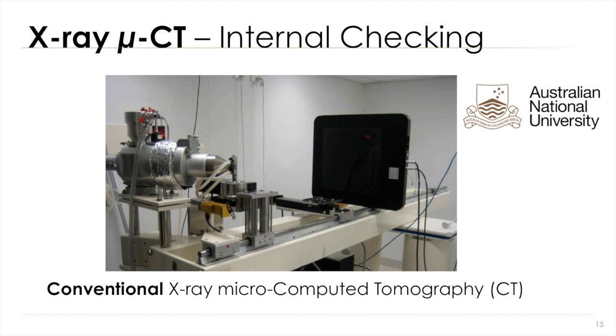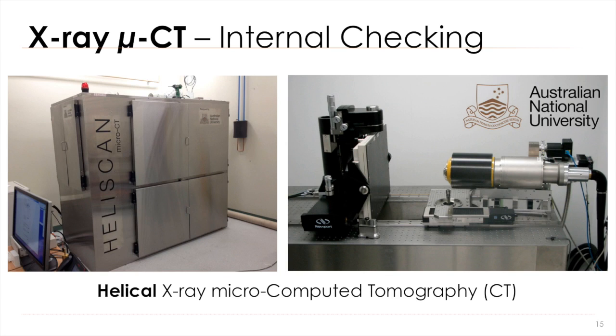Then, the second technique, using X-ray micro-computed tomography, we used to look at internal checking of OSB. We used 2 X-ray computer tomography devices developed at the Australian National University to gather the datasets of the internal microstructure of OSB samples. So the first, a conventional system, and then the state-of-the-art high-resolution Helical X-ray CT. This device gives us better resolution and more signal-to-noise ratio compared to the conventional X-ray CT device. So we focused on the analysis of the datasets obtained by the Helical system.